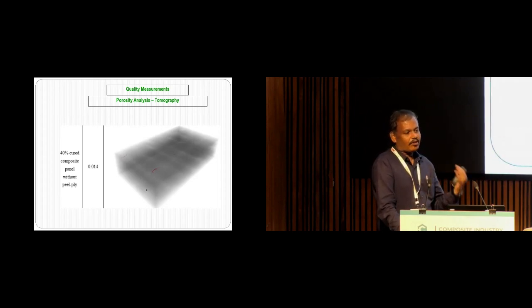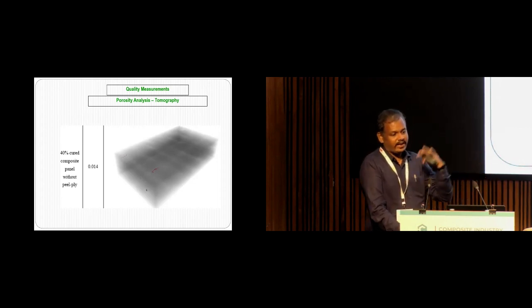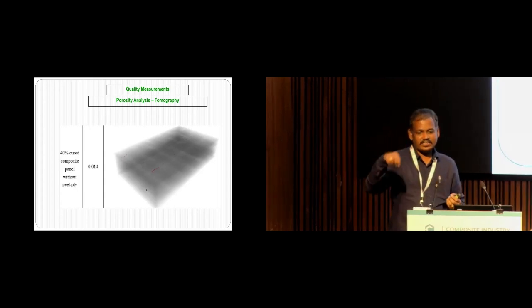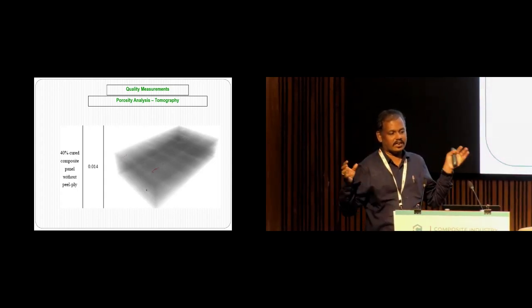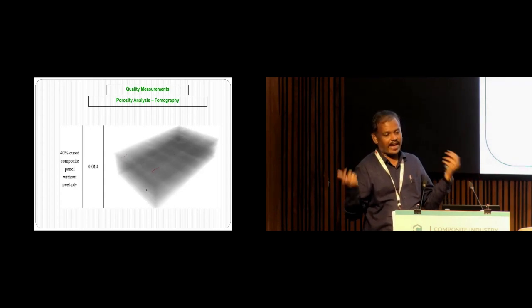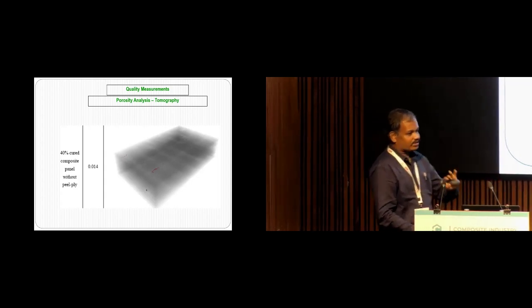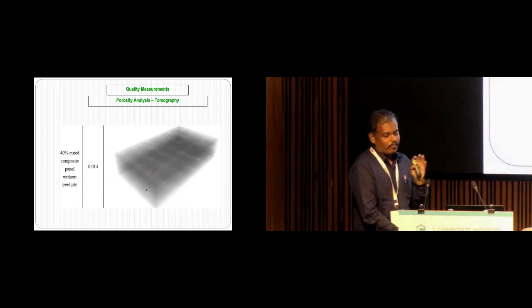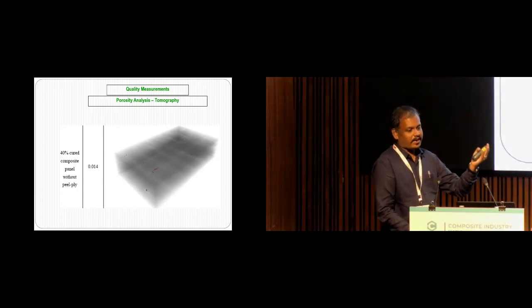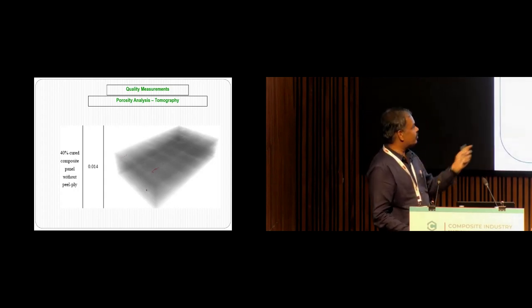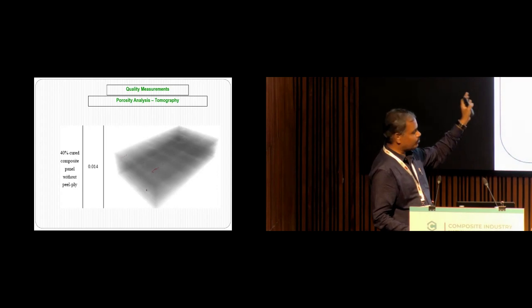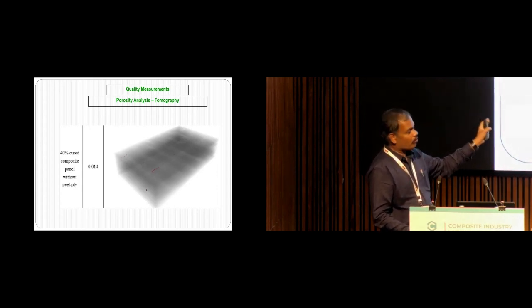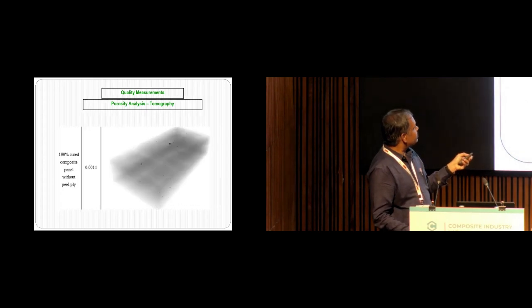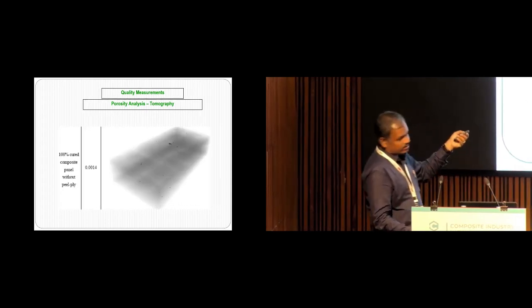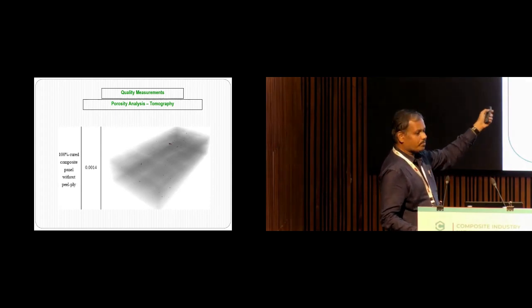we have used vacuum enhanced resin transfer molding. This is not simple resin transfer molding; it is vacuum enhanced. At the injection port you have the injection pressure, but at the exit port, the exit vents, you have vacuum attached. With that process, what we have achieved is that we can manufacture aerospace grade within the RTM process itself. Since this is a very important parameter, where you should have less than 0.1% pore volume, we are able to achieve it. This is for a 100% cured composite panel. This is also showing a very low pore volume percentage, this is volume percentage actually.